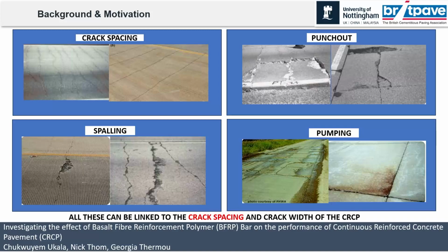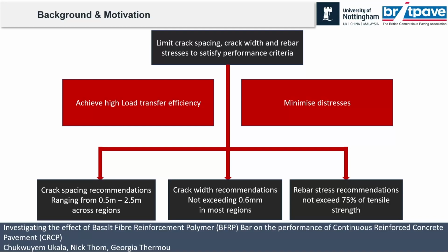So punch out and spalling are the main distresses we see in CRCP. Because of that, we try to get proper CRCP structural designs to minimize or eliminate the effects of these. There are other, minimal distresses, but the typical ones we look at are punch out and spalling. So design processes have been established more or less to look at three critical areas. Design tends to keep our crack spacing at a range that research has shown will be able to limit the spalling and the punch out of the concrete.